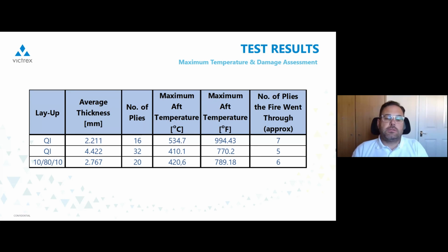So after 15 minutes of fire at 1100 degrees C, the fire went through 7 plies. So I lost 7 out of my 16 plies. I'm saying this because, depending again on the fire designated zones that I mentioned in the first slides, this is important. Depending on what you're manufacturing, where that sits on an aircraft engine, there are requirements for some structures to also have some post-fire structural integrity. So that's why I have it here. It could be of interest to the audience.